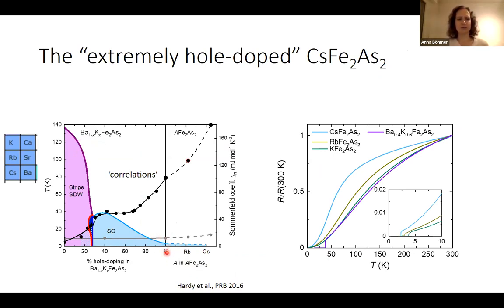We can go further, now vertically in the periodic table, so apply chemical pressure to the rubidium and the cesium compound. And if we go in this direction, we see that the Sommerfeld coefficient, the specific heat coefficient, the effective mass or measure of the correlations, goes up quite a bit. So these are very large values. This comes in the region of heavy fermion compounds. The resistance also looks similar to heavy fermion systems. There's a huge residual resistivity, and there's an almost quadratic or power-law-like temperature dependence at low temperature here. And there are superconductors around 2 or 3 Kelvin.